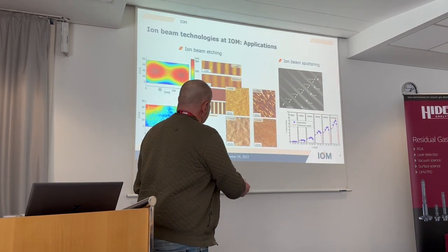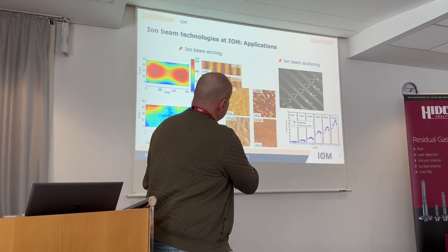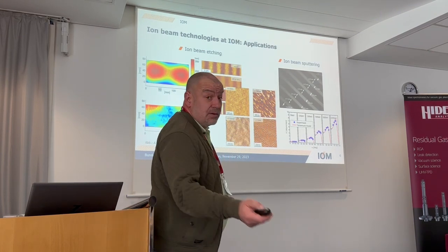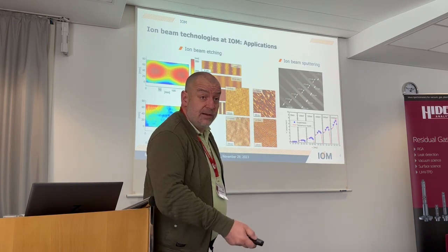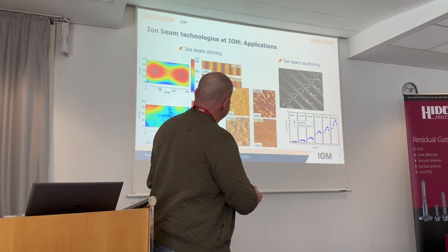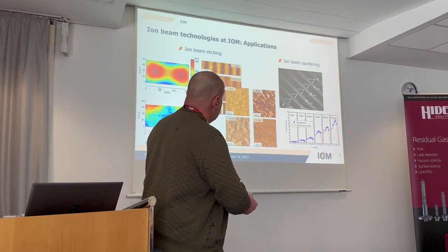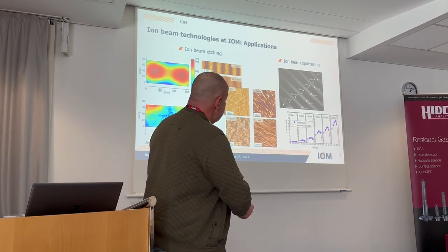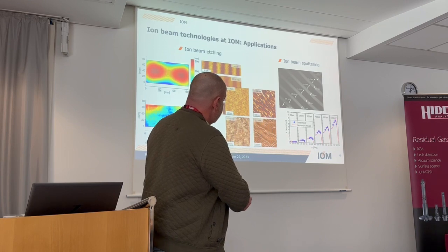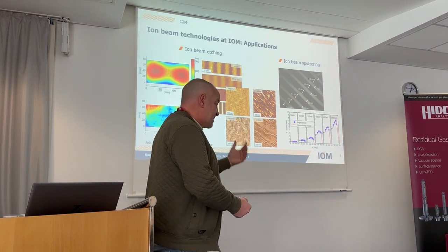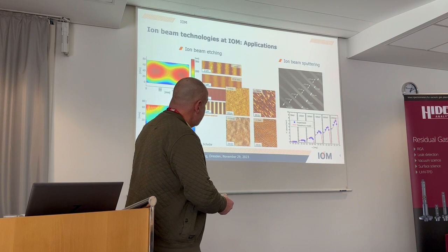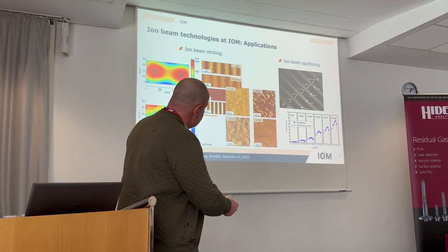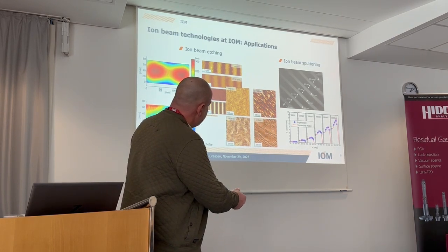And here's some ion beam sputtering. We have here some thin films. You know it much better than me; you probably did much better pictures and multilayer coatings. As I said, we are mainly related to fundamental processes. So you have here the sputtering yield, the number of sputtered atoms per incident ion, in dependence on the ion incidence angle for different ion energies.